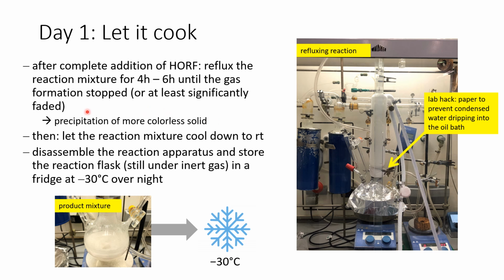After all the alcohol has been added to the reaction mixture, we reflux the reaction for 5 to 6 hours until the formation of hydrogen has almost stopped or at least significantly faded. During this time, we see a precipitation of a lot of colorless solid in the reaction mixture. As a small lab hack, it is always good to attach a paper towel here to prevent ice or water from coming into the hot oil bath beneath it.